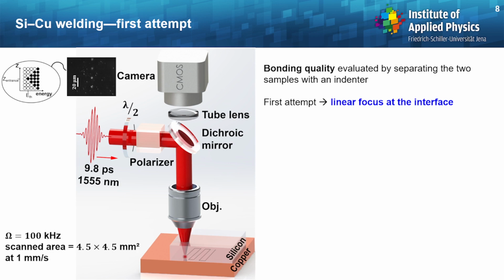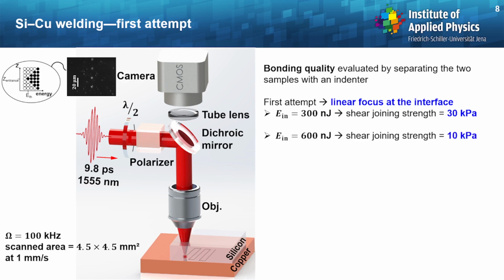All right, so let us have a first attempt, and let's try to simply position the linear focus at the interface between silicon, and here metal is illustrated by copper. Let's set the input pulse energy to 300 nanojoules, okay? And now we measure the shear joining strength, which is on the order of 30 kilopascal, all right? What about now doubling the input pulse energy and going to 600 nanojoules? Well, then the shear joining strength, interestingly, is 10 kilopascal. So you double the input pulse energy and you get 3 times less shear joining strength.